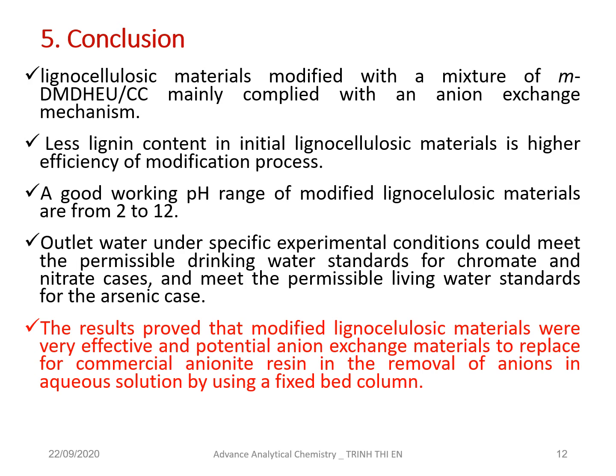And the treated water, especially under specific experimental conditions, could meet the permissible drinking water standard for chromate and nitrate, and meets the permissible living water standard for arsenic. And especially, the research showed the modified lignocellulosic material is a very effective and potential anion exchange material to replace commercial anionite resin in the removal of anions in aqueous solution using a fixed bed column.